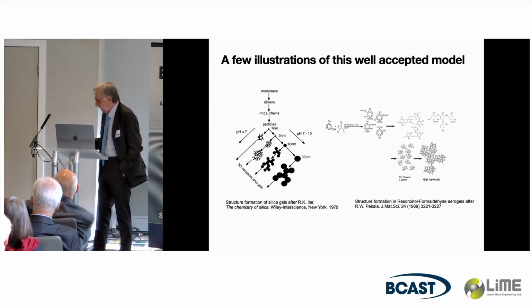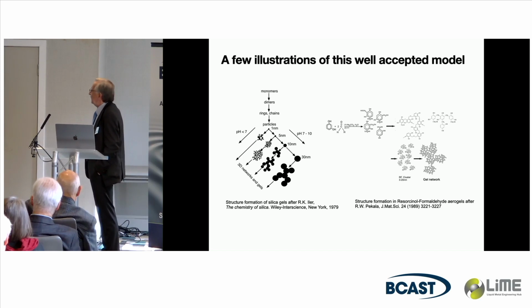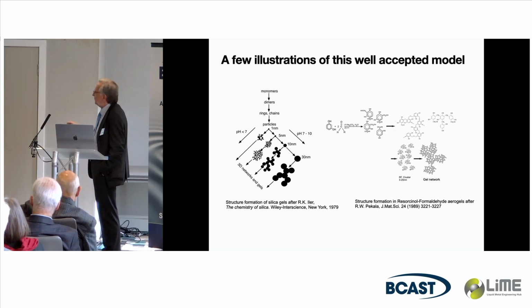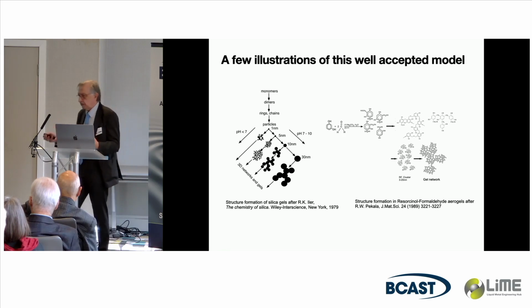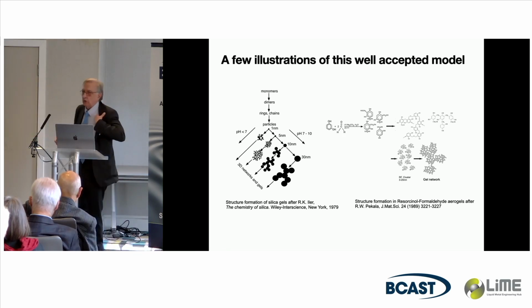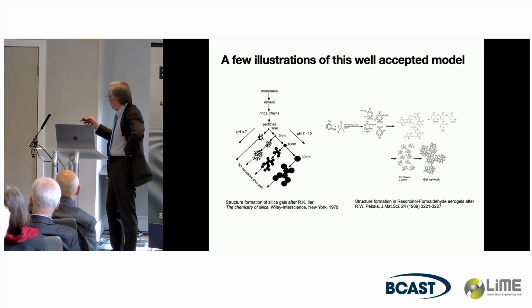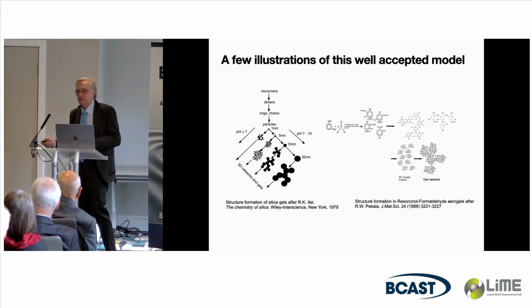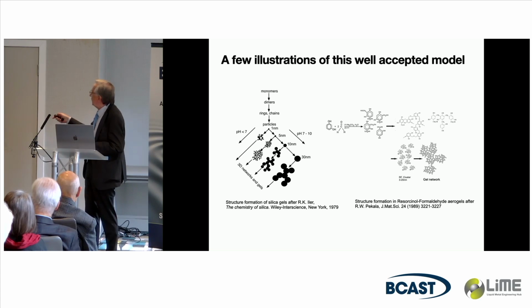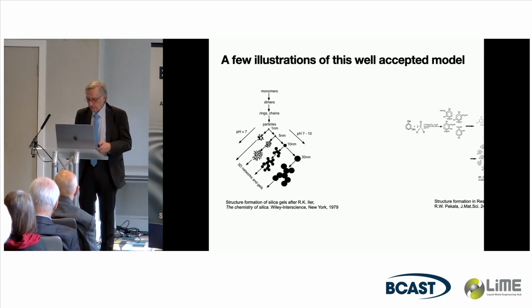So, a few illustrations of this model. This goes back to a wonderful book of Ralph Iler on silica gels. If you do it in acidic conditions, working with silica, you get a fractal network. If you do it under base conditions, you get bigger particles, used to study, for instance, colloid crystals. And this is the same done a few years later with resorcinol, which is a dihydroxybenzene. You have two OH groups that react with formaldehyde, build methylene bridges or methylene ether bridges, make a gel network, and that's it.